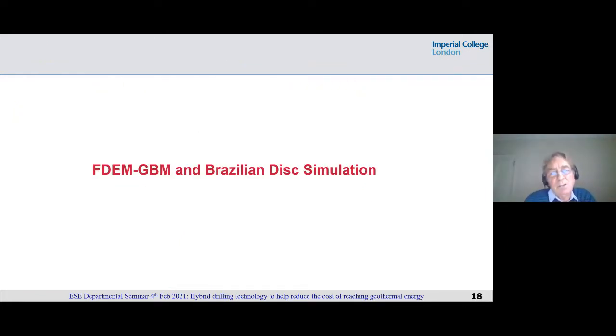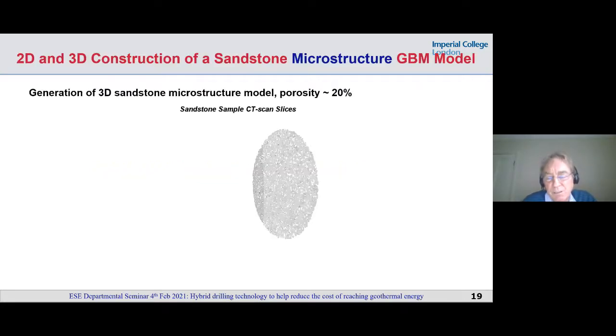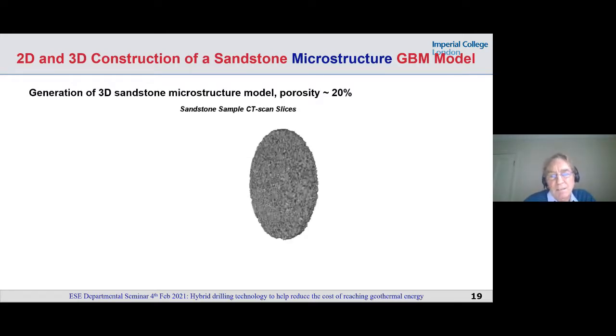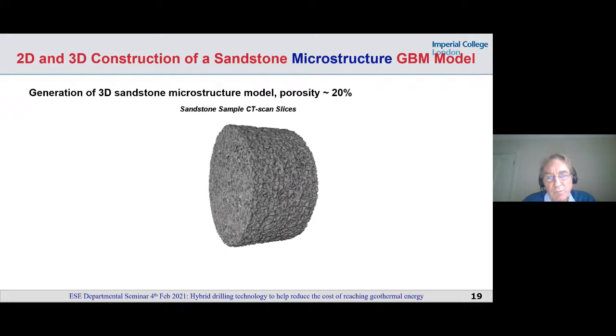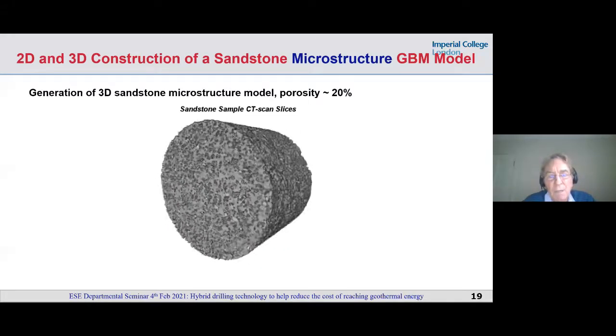So now I just introduced, we're getting down to modeling the grain-based microstructural part of the material, and we're going to subject it to Brazilian disc compression and tensile failure. So now we're going to look at the 2D and 3D construction of the sandstone and the microstructure. Here we have, this is how we capture it. We capture it with a CT scan technique. So this is the first slice, and this is building up the 3D geometry of this 20% porosity sandstone.